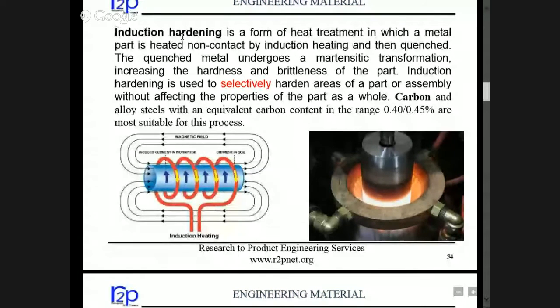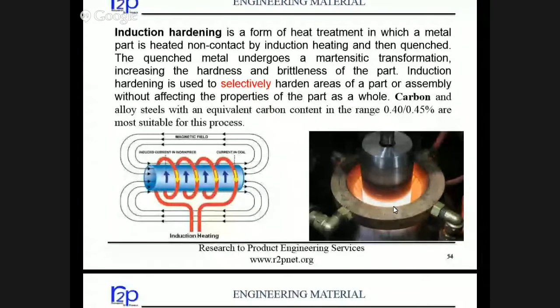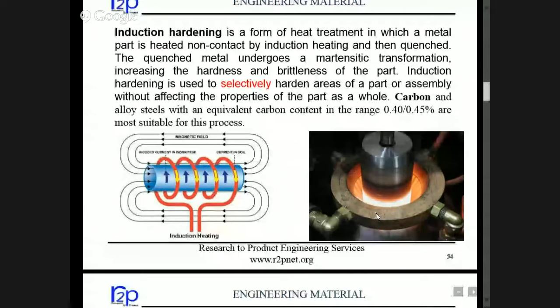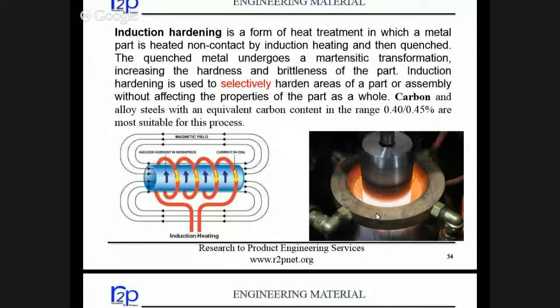Now we see the induction hardening steel. In the induction hardening process, you have seen that heating of the surface happens by the eddy currents generated by a medium frequency or a high frequency machine. Another difference vis-a-vis case carburizing is that it's a very fast operation. The whole operation can be completed in 2-3 minutes, while in case carburizing you see maybe 8 to 10 hours, then tempering. So the whole process is very cumbersome and long, right?